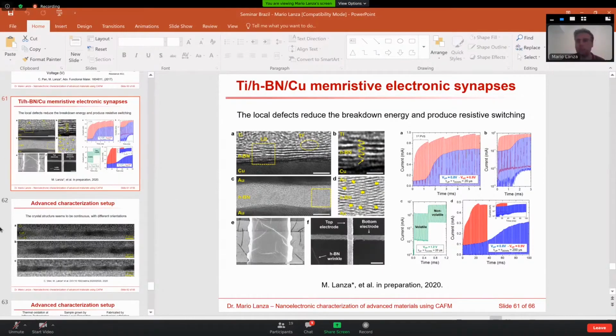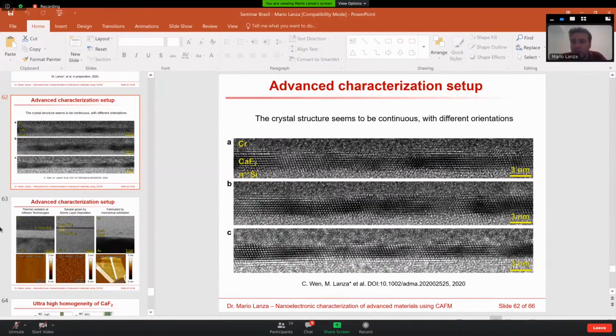So this material is grown by molecular beam epitaxy. Actually, there is a big difference comparing the boron nitride with the calcium fluoride: the calcium fluoride can be grown at 250 degrees, while the boron nitride is normally grown above 700 degrees. So the thermal budget is totally different, and it is realistic to think that calcium fluoride could be grown on a wafer with something patterned on it, so it will not destroy what is in the wafer.